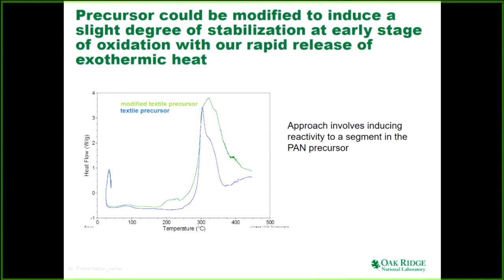So what we have done is develop a recipe for these precursors or any other precursors where you can treat the fiber on its surface, and then it would induce the oxidation rate slightly better. And I don't want to perturb their kinetic parameters too much.